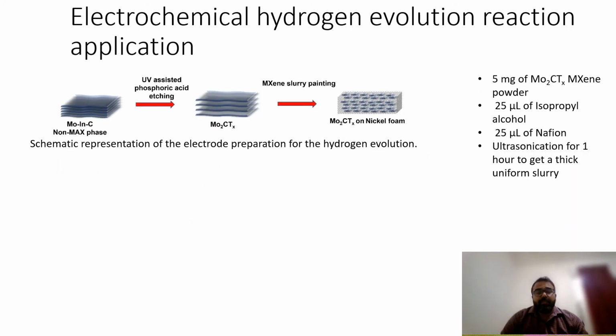Then we have studied the performance of MXenes as an electrocatalyst. For that, we prepared electrocatalyst of MXene on a nickel foam. For that, we used 5 mg of the molybdenum carbide MXene powder in 25 microliter of isopropyl alcohol and 25 microliter of Nafion, ultrasonicated for a period of 1 hour to make a thick slurry. And this thick slurry was deposited on a nickel foam and dried overnight to get a uniform deposited MXene on the nickel foam, which serves as the working electrode for the hydrogen evolution reaction.